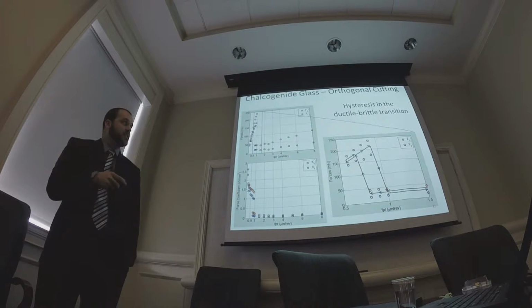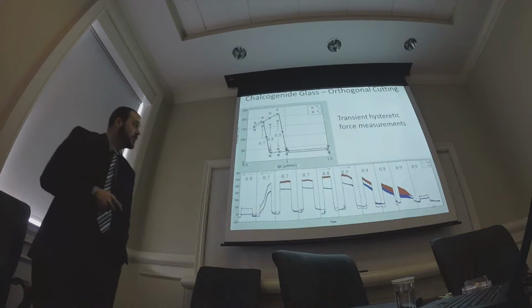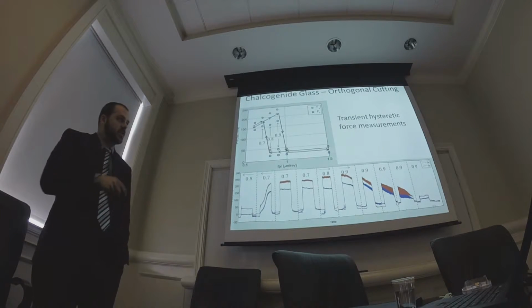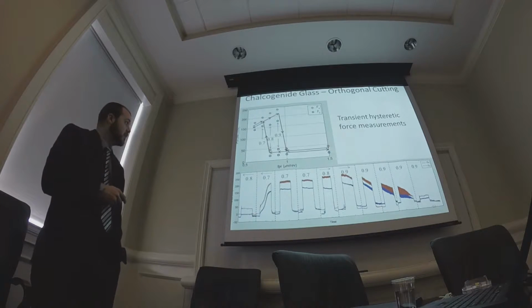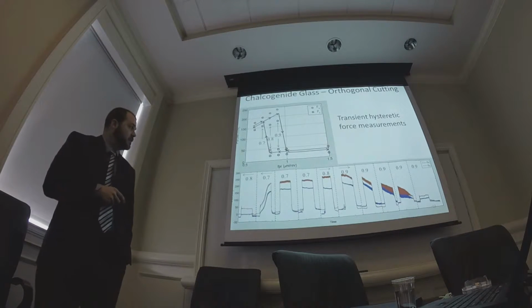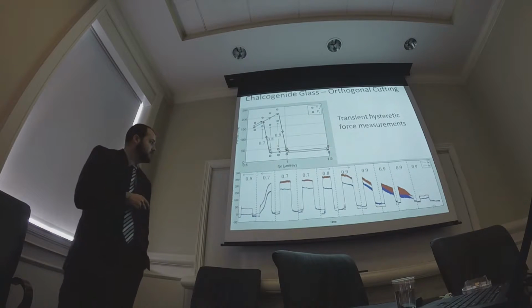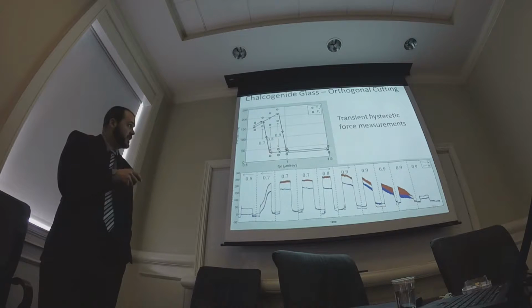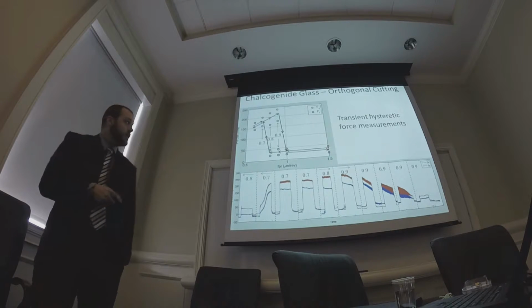But at 800 or 900 in here, it would depend on what the surface was before. So here's a couple of tests that kind of show that and show the transition I was talking about. So here we've got a point down here in this 800 nanometer, or 0.8 micron range. We've got down here, so this is what I'm calling brittle dominated.